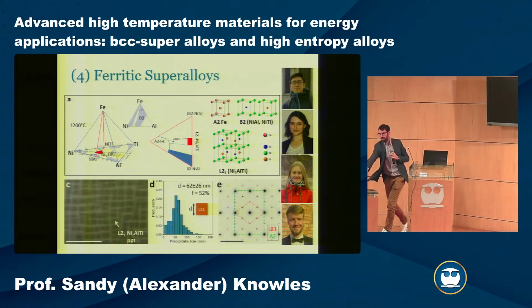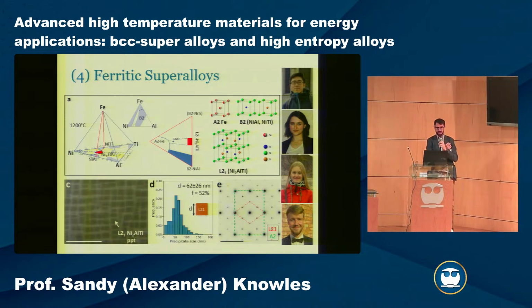The last of the BCC superalloy systems is this one class of ferritic superalloys. We have quite a large number of people working on this in the group. It's quite an attractive system, based on iron and aluminium. As you add aluminium into a steel, you reduce the density, so that's quite attractive if you're trying to lightweight automotive and other applications. And again, we're taking this microstructure concept of a BCC iron base, with these ordered intermetallics as the reinforcing phase. You can form these cuboidal gamma-gamma prime-like microstructures, but instead now we're, I guess, alpha-alpha prime, if we're using steel nomenclature.